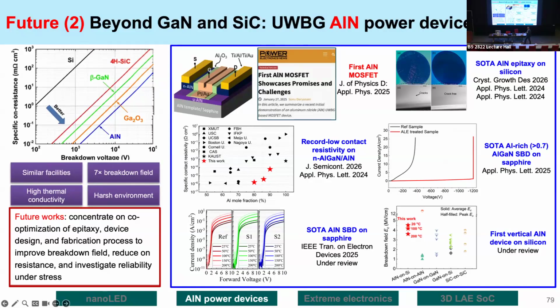So in my group, we have done a lot of preliminary works related to aluminum nitride power transistor. For example, last year, we reported the first aluminum nitride MOSFET. Because as you know, most of the power transistors today are all MOSFET. Most of the CMOS are also MOSFET because it's the most stable and scalable transistor technology. So by developing the first aluminum nitride MOSFET, we actually have a very solid foundation for future development. And also we have done work related to very low contact resistivity on the N-type aluminum nitride. And also we have demonstrated several state-of-the-art results, for example, the state-of-the-art aluminum nitride epitaxy on silicon by MOCVD, and also the aluminum gallium nitride and aluminum nitride SBD with high breakdown voltage.